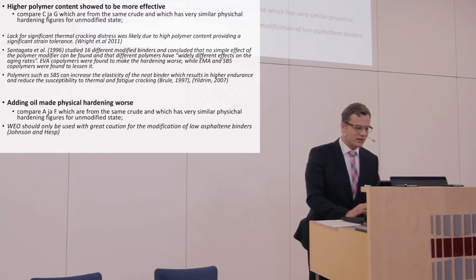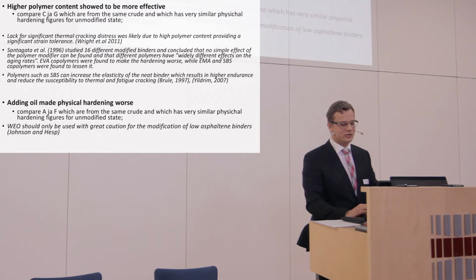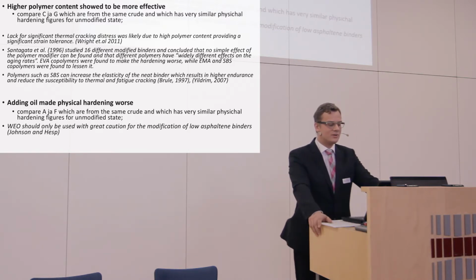Wright et al. 2011 wrote that lack of significant thermal cracking distress was likely due to high polymer content, providing a significant strain tolerance. Santagata et al. (1996) studied 16 different modified binders and concluded that no simple effect of the polymer modification can be found, and that different polymers have widely different effects on the aging rates. EVA copolymers were found to make the hardening worse, while EMA and SBS copolymers were found to lessen it.